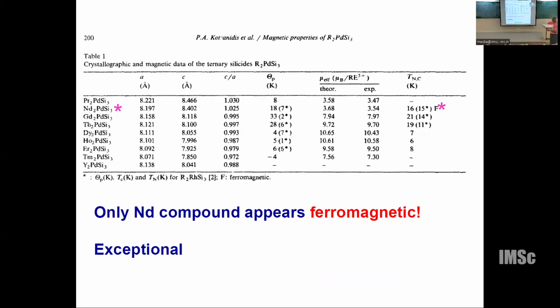If you look at it, neodymium here, look at this, ferromagnetic. And the other ones are antiferromagnetic. You see an anomaly here. And we have shown here in neodymium also your 4f is participating in bonding. Unlike in other cases, there is no bonding. So 4f participating in bonding can change the magnetic characteristics. It's a very clear-cut example.